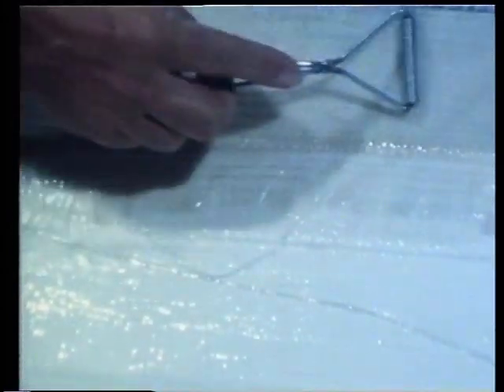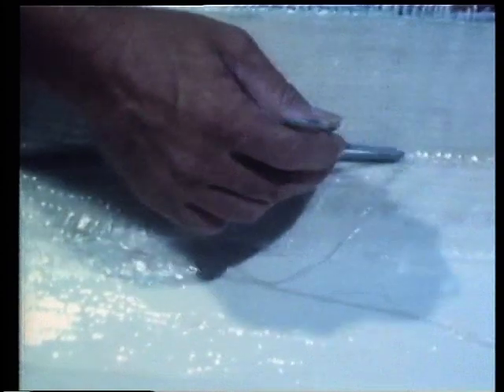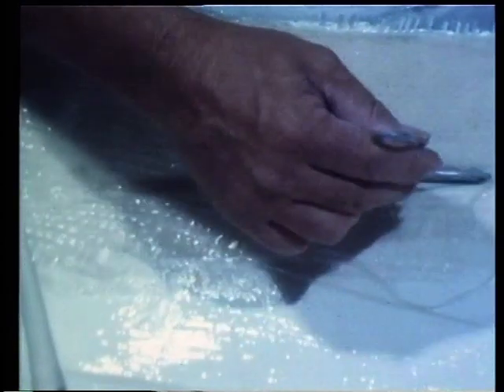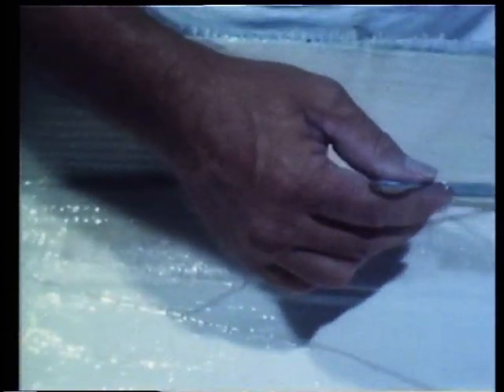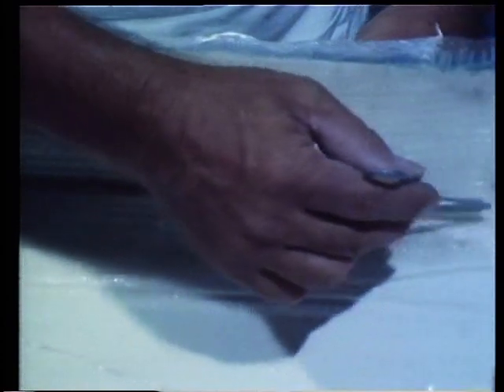Now it takes the roving a little longer to wet out than it does the mat, because obviously it's quite a thick material and those straight strands of roving, such as that one there, are really quite thick. It takes a little more work with the compressor roller and with the brush to work the resin up through it. But your indication that it's fully wet comes when all of the white colour disappears and it goes completely clear. Again, bubbles are extremely easy to see because they show up with a silvery colour on them down inside the moulding there.